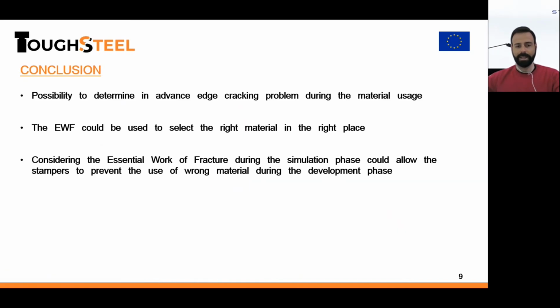So based on that, we can say that there is the possibility to determine in advance the edge cracking problem. The essential work of fracture could be used to select the right material in the right place, hopefully in advance of having the first pieces stamped. And if we are able to consider the essential work of fracture during the simulation phase, this could allow us and the stampers to avoid using the wrong material, and also to work to solve the stamping problem.